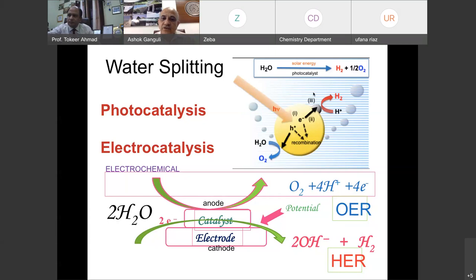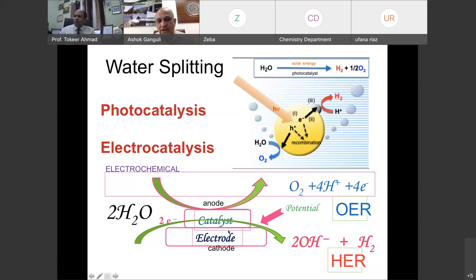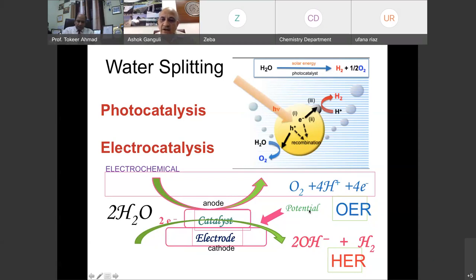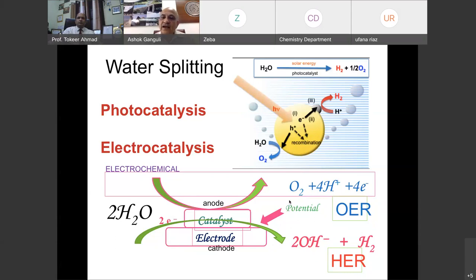When designing semiconductors for photo electrochemistry, you want two key properties: maximum absorption of photons, and stability so they don't get photo corroded. They should be stable, have long lifetime, and allow high lifetime of charge carriers. A typical semiconductor band diagram has a conduction band and a valence band. When light falls, electron-hole pairs are generated. These holes and electrons need energies that match the reaction you want to do — for example, oxidizing water requires the energy level to be at a particular position.